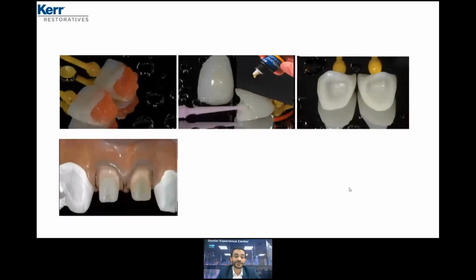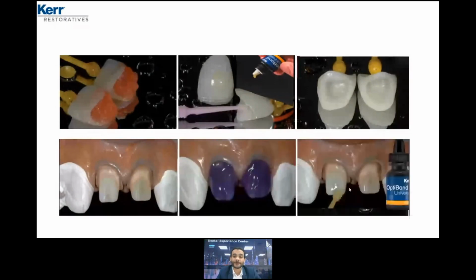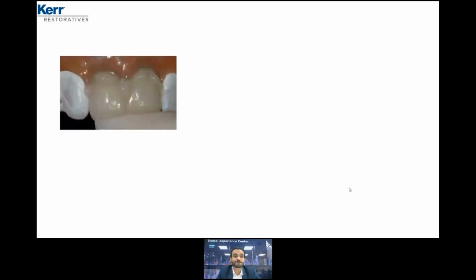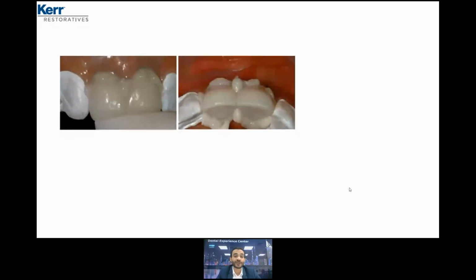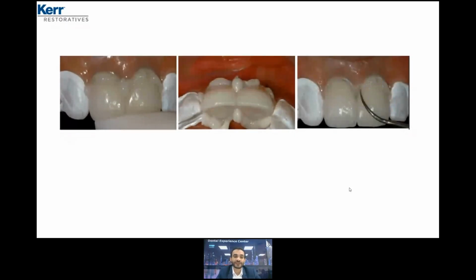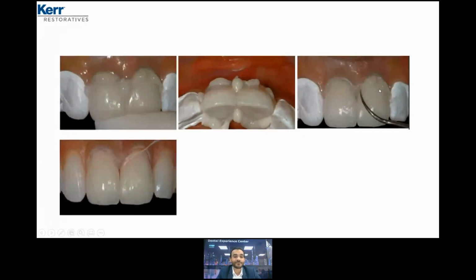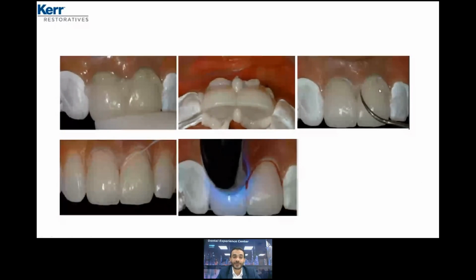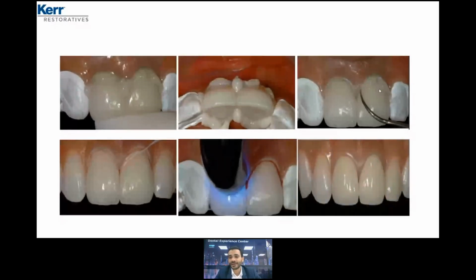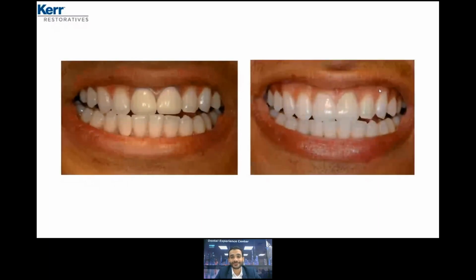Going into the tooth treatment, acid etch. Apply OptiBond Universal. Use the try-in paste in order to check, or directly after the try-in you can apply the cement, remove the excess, and light cure. And actually, as I told you, you have a dual cure cement and the light cure cement. The dual cure cement is slightly lower in viscosity in comparison with the light cure cement. And here we can see the pictures before and after.